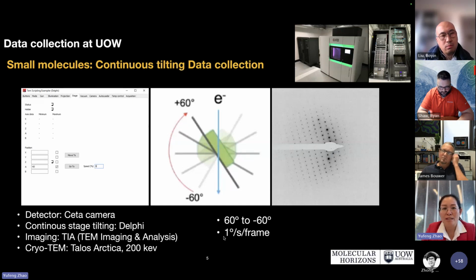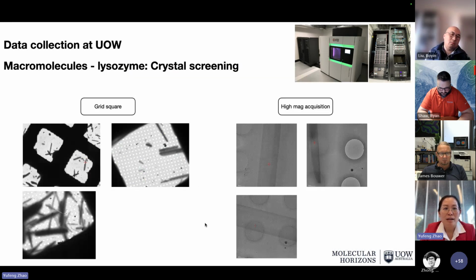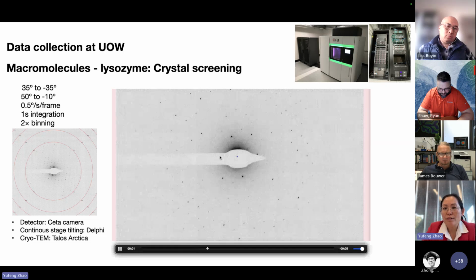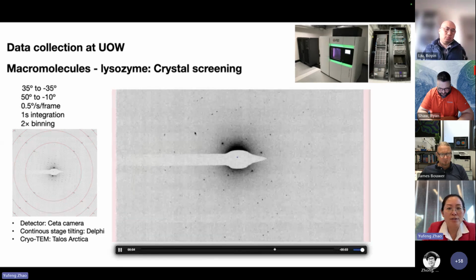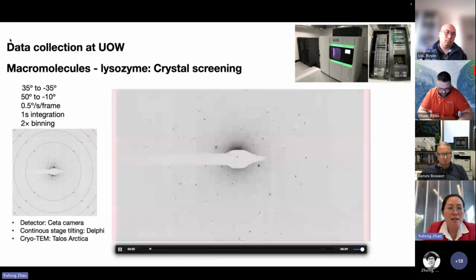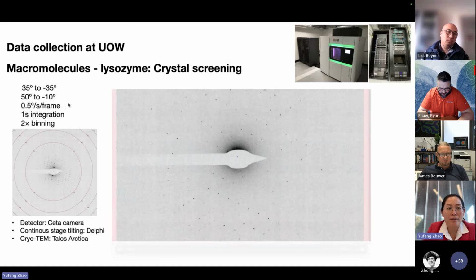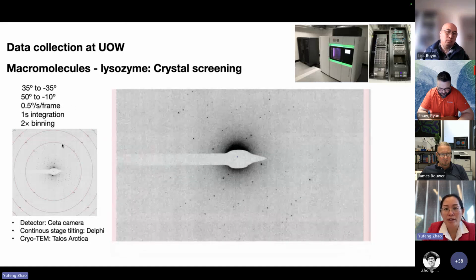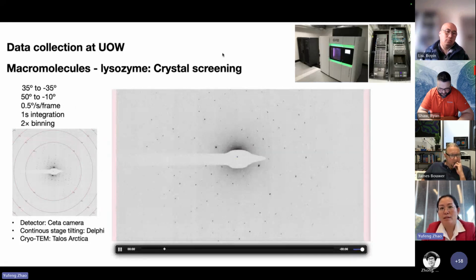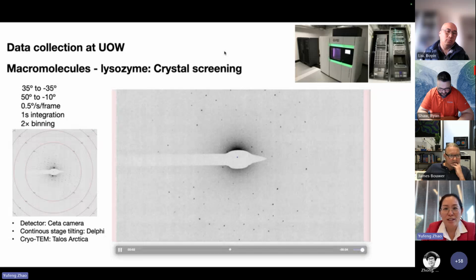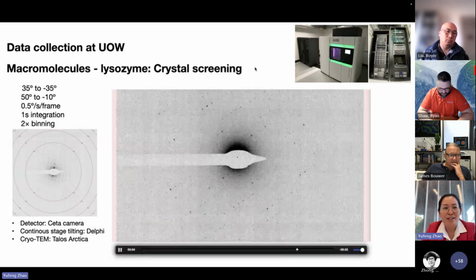For small molecules, Boyan just recommended, we do a similar thing. We normally use a big range, 120 degrees. And for proteins, here's our protein image from last year, a special lysozyme. Similar for macromolecules, we just adjust the tilting angle and integration time to get the best data before the crystal dies in the radiation.